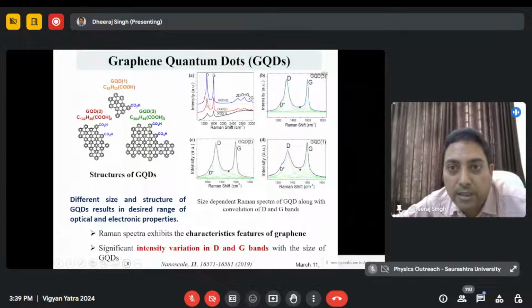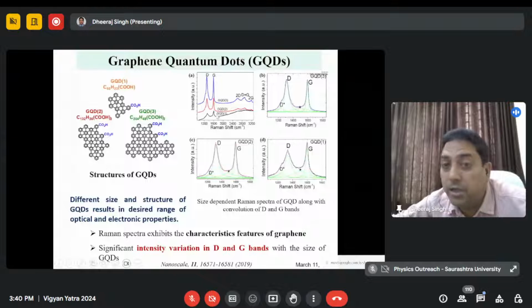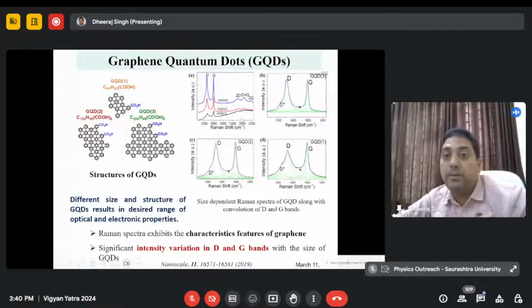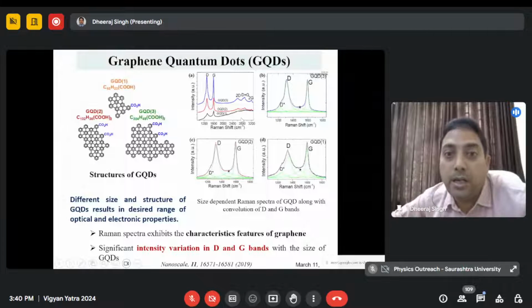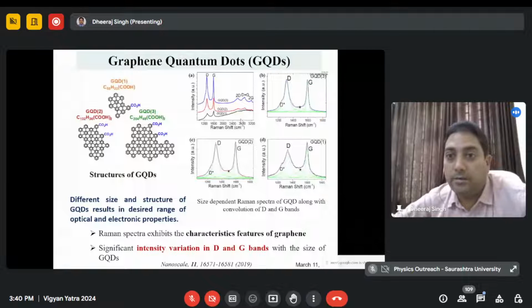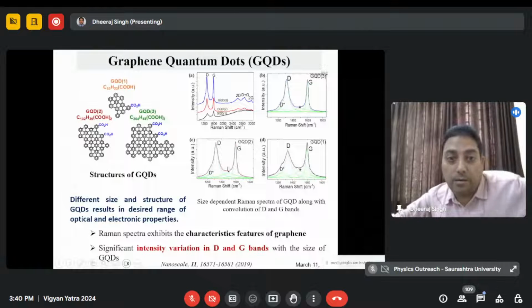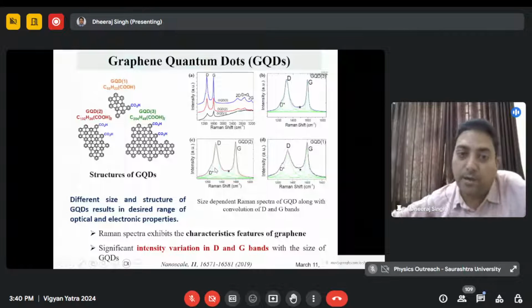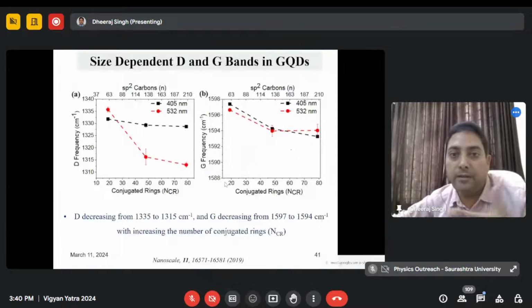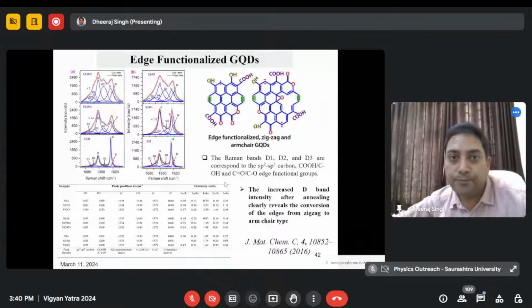In the spectra, you can see graphene quantum dot 1, graphene quantum dot 2, graphene quantum dot 3. So what are the changes? You can see that the intensity ratio of the D and G bands is changed. Here the second intensity is larger, but here the intensities are almost equal. So the ratio of the intensity can change, and it clearly identifies that particular quantization. Quantization means that graphene quantum dots, with significant intensity variation in the D and G bands, can be characterized by their size. And this is a graph of what we have explained.